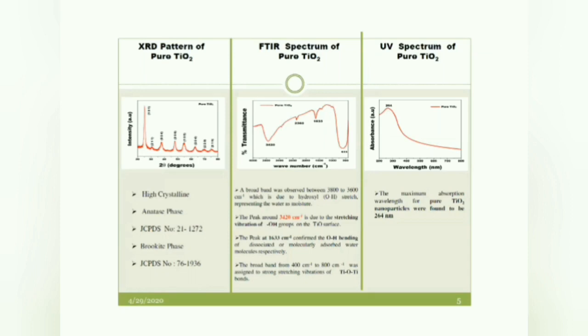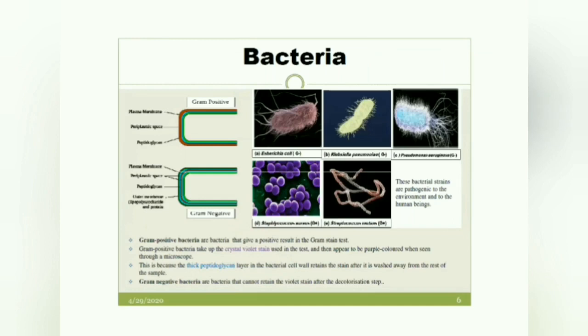And in the case of the FTIR spectra, the Ti-O bond stretching around 633 denotes a strong stretching vibration of titanium dioxide. And from the UV spectrum, we were able to see the maximum absorbance comes around 264 nanometers. So from all these things, we were able to understand it is titanium dioxide nanoparticles. Our work is under biological application, which is antibacterial.